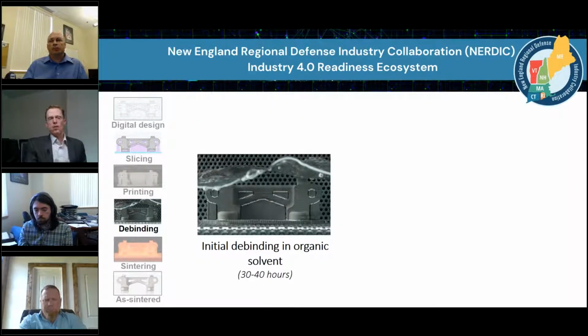Once the part is printed, it then goes to an initial debinding process, typically an organic solvent. The time it takes for the debinding process depends upon how thick the sidewalls are. So for something that has this three wall layer, maybe like an outer wall and two inner walls, it's going to take less time than something that has maybe 6 walls or 10 walls.